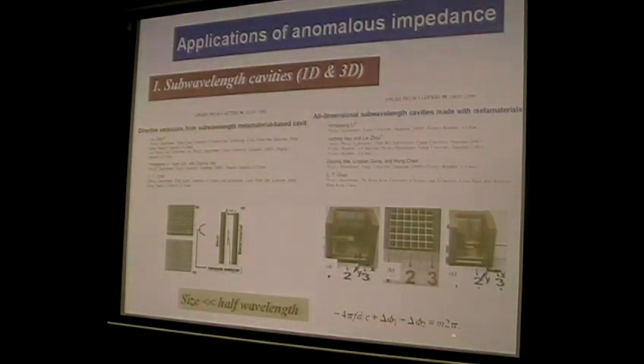For conventional materials, the delta phi for 2 interfaces is just pi, so nothing special happens. However, if we replace one of the materials with a metamaterial, because the delta phi can take any value, immediately you will find that the size is not bounded as half wavelength at all. It can have a much smaller thickness of this cavity. And indeed, we did an experiment to show that for this special arrangement of cavity, we can have a subwavelength effect. And also we extended the idea to 3 dimensions, and fabricated an all-dimensional subwavelength cavity, which is not bounded by the half wavelength at all.